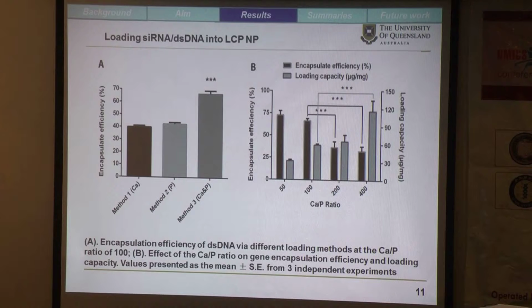Then the LCP nanoparticles were used to encapsulate the siRNA, mimicking with the label dsDNA, using 3 different methods. As shown in the picture, obviously, method 3 led to the highest encapsulation efficiency, where half amount of dsDNA was separately mixed with the calcium and phosphate solution. After that, the encapsulation efficiency and loading capacity of LCP nanoparticles prepared using method 3 at different calcium to phosphate ratio were tested.